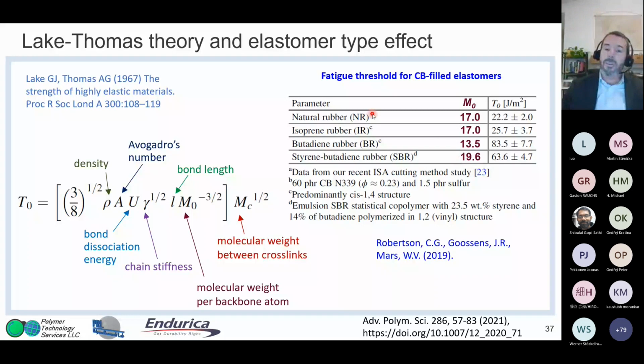And what you see is if you compare natural rubber and butadiene rubber, the M sub 0 exactly explains what's going on. You get a much smaller M sub 0 for butadiene rubber, and you get a much higher fatigue threshold, 80 instead of 20. SBR is not just an M sub 0 effect because SBR also has higher chain stiffness. So that one needs chain stiffness to come into the discussion to understand where it fits. But the relative ranking is lowest is natural rubber, highest is butadiene rubber, and in between is SBR.